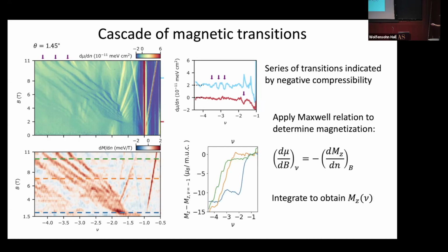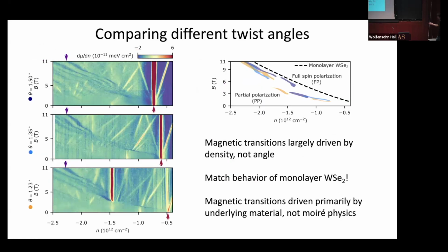So the last point that I'd like to make is that if you measure at different local twist angles, in all cases you see this series of dark blue features that correspond to the magnetic transitions that we were talking about before. But here they're plotted not as a function of filling factor, but as a function of overall carrier density. And interestingly enough, when plotted in this way, these magnetic transitions more or less all fall in the same window of carrier density and magnetic field space. So I've just plotted the first one for you here, color-coded by twist angle. You can see that they all sort of overlap.